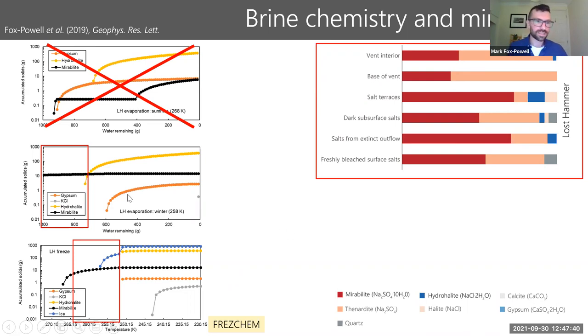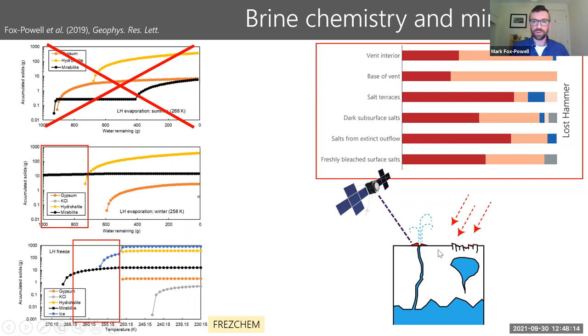And moreover, what we are seeing is a snapshot of the early evolution of this fluid. Mirabilite, this black trace here, in both the evaporation and the freezing case, is the dominant phase here. So we're looking at an early snapshot of the evolution before we start precipitating lots and lots of chloride, which is what we predict would form towards the end of freezing or evaporation. So this is not a complete representation of the brine. And of course, this is very important if we think that on a moon like Europa, we will be only looking at these salt deposits. So we need to understand the potential for a deposit like this to become fractionated away from its original source brine.